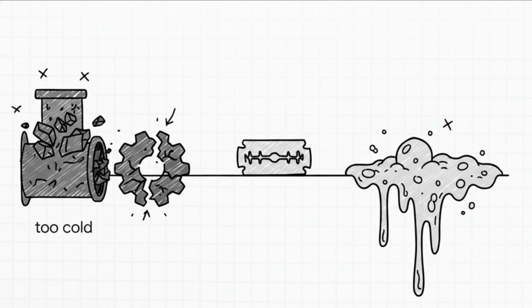If the temperature drops even slightly below the polymer's crystalline melting point, the plastic just refuses to flow. This leads to immediate clogging, severe pressure spikes, and ultimately catastrophic structural failure where the machine's drive gears literally shatter under the sheer strain. But if the machine runs too hot, well, we face a completely different disaster. The polymer chains undergo rapid thermal degradation, which we call chain scission. This introduces these tiny gaseous microvoids into the plastic, which entirely ruins the finished material's mechanical strength and its look. The margin for error here is razor thin.